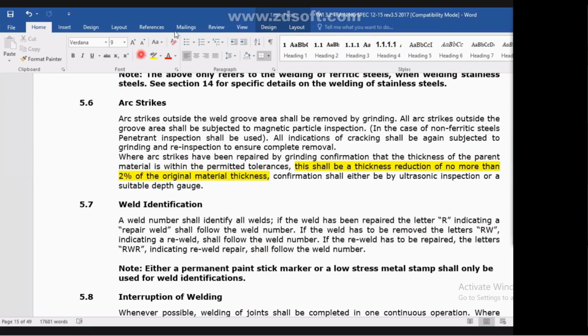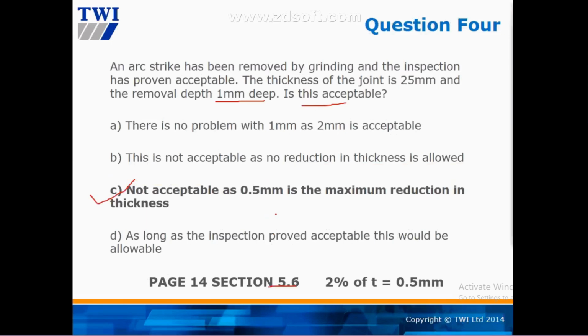All right. So now we do some calculations here. So the thickness is 25 here. Then we times 2%. So that will give us the answer 0.5 mm. So 0.5 mm here is the maximum reduction thickness. But here we got 1 mm deep, which is over than 0.5. So that's where the answer goes to C. Not acceptable, as 0.5 is the maximum reduction in thickness. Got it? Yeah? All right.